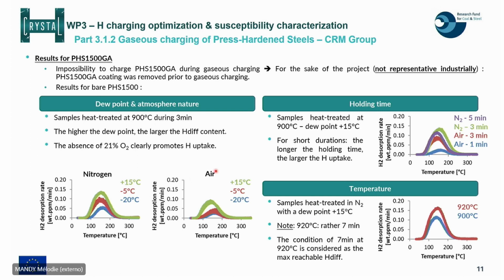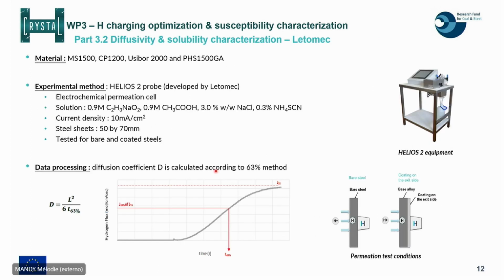So that was for the hydrogen charging. Now in terms of characterization of the system, at Letomec, they were able to characterize the diffusivity and the solubility of the four materials that we work with in the crystal project, owing to a specific tool that they developed. It's called the Helios 2 probe. It's based on the principle of an electrochemical permeation cell, but with a solid state sensor.